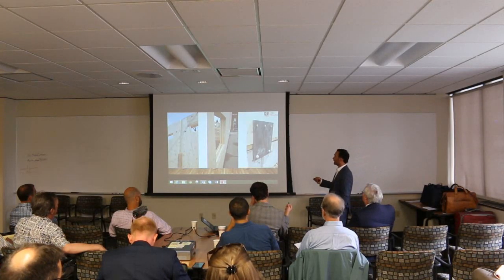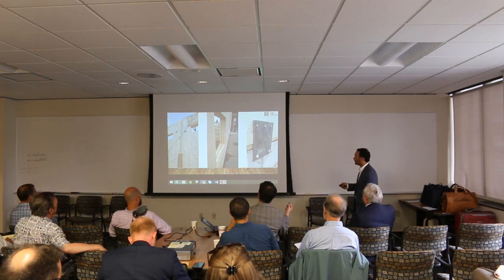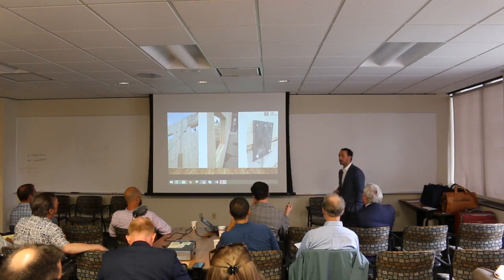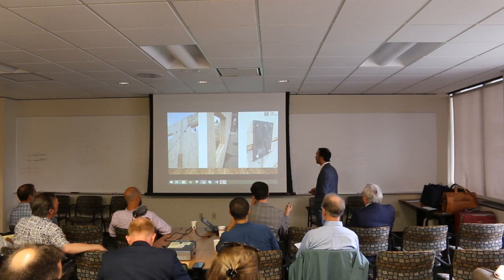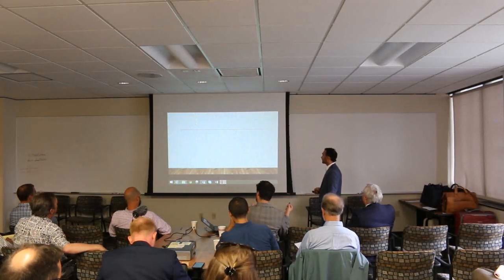Some of the things to think about is they're pretty rough when they come. Some of them look pretty good, but others are rough. They definitely need cleaned up, and you can't leave them exposed. You have some lower grade lumber on the interior, maybe a little bit of checking and cracking, some glue exposed here and there. So it's definitely not a finished look on your window openings.